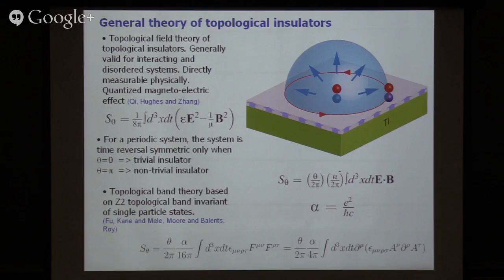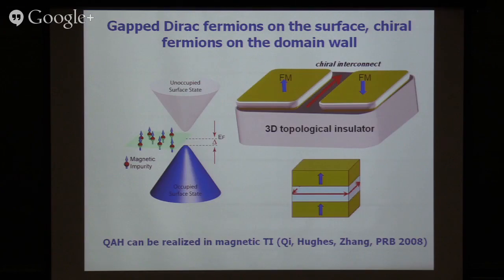Because under time reversal symmetry, theta equals pi will go to theta equals minus pi, but they differ from each other by 2 pi, which is the period, which doesn't change physics. So interestingly, a topological insulator can be defined by a theta equals pi kind of response. That is topological because this is in principle a magnetoelectric effect that can be experimentally measured. Inside the topological insulator, if you change things a little bit, the magnetoelectric effect will not change; it stays invariant. So there's something physically measurable, which is a topological invariant, and that's the precise sense in which this is topological.